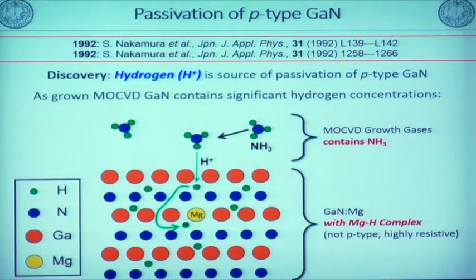Basically, we use ammonia gas for the gallium nitride growth. Ammonia gas is dissociated into atomic hydrogen. The atomic hydrogen combines with the magnesium acceptor, forming a magnesium hydrogen complex. So the magnesium acceptor is passivated by atomic hydrogen. That is called hydrogen passivation. But using thermal annealing, we can remove the atomic hydrogen from the magnesium hydrogen complex, and we get P-type gallium nitride. Also using an electron beam, we can remove the atomic hydrogen from the magnesium hydrogen complex. That's the reason we got P-type gallium nitride using thermal annealing.